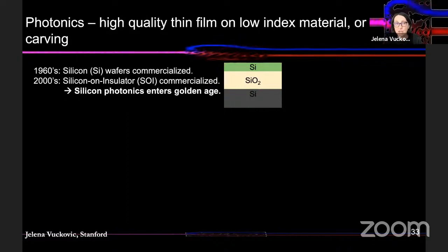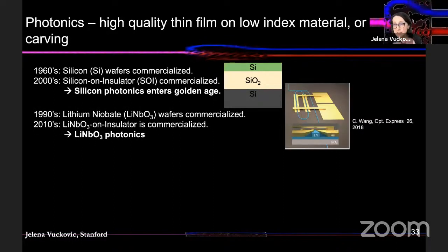And when you're building photonics, you need some guiding layer, a high index layer on top of some low index layer, as people do in silicon. For those of you who are younger, you may not know that these silicon on insulator wafers that people use for silicon photonics today were commercialized only about 20 years ago. That was 40 years after bulk silicon was first commercialized. And this is really when the whole silicon photonics field took off. And about 10 years ago, people commercialized thin film lithium niobate on insulator, again about 20 years after bulk lithium niobate was commercialized. And that's when the lithium niobate photonics field took off, which is very active today.